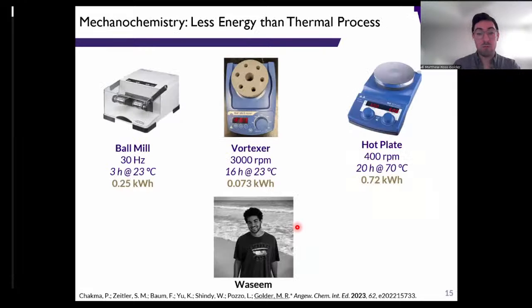These free radical polymerizations are inherently more sustainable, at least at a first approximation level in lab scale, right? This isn't talking about an industrial process. We're just comparing apples to apples here in our own lab. Thinking about the expedited profile in the ball mill, we can run the reaction for about 3 hours. We're not applying exogenous heat. We're using about 1/4 of a kilowatt hour for this entire process to occur.